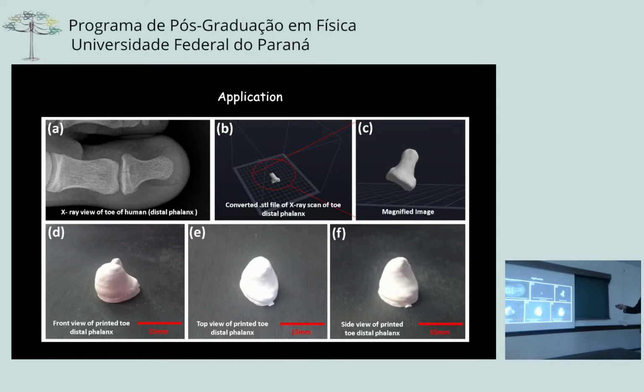What you see here is the toe, the big toe finger in your leg. Generally, if you hit somewhere, it's going to break. Now, the conventional joints like elbow and so on are available quite frequently. But if you have a breakage like this, you don't have a commercially available solution. And if it's kids, it's even worse because you don't really get it in the market. What you can do here is you take this scan, look at the broken piece, and you can 3D print with a similar resolution. It has good strength, good ductility, all the mechanical properties that you need. Apart from that, cells love growing on top of it, right? So it's biocompatible, bio-friendly. We started working on this, printing several of them and trying to look at its application. That's the direction where we are moving.